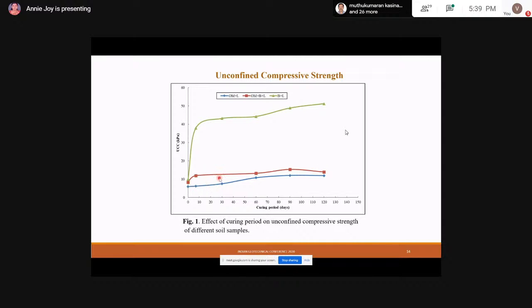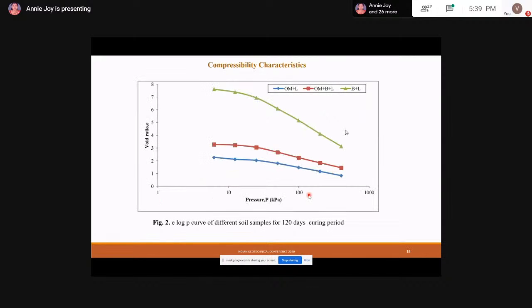Now we could see that in the case of soil mixture containing organic matter, there is an aggregation of organic matter due to which flocks are formed. So initially we could observe an increase in strength, but as time progresses, this organic matter coats the clay minerals, inhibiting the reaction between lime and clay mineral, which led to the decrease in unconfined compressive strength. Next is the void ratio pressure relationship.